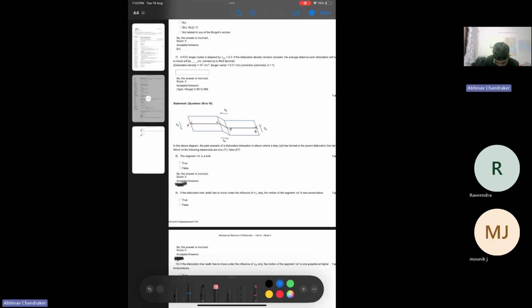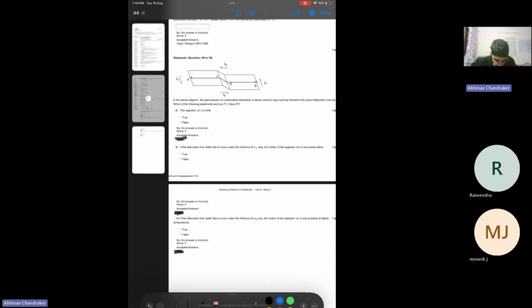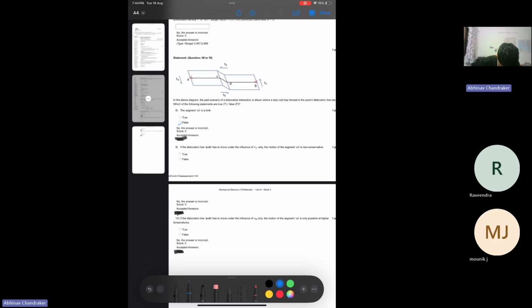Actually, if this is a screw dislocation, it cannot be, because CD has a different direction compared to BD. So the Burgers vector of BD will not be the same as that of CD if this is a screw dislocation, because a screw dislocation has its Burgers vector along the dislocation line. So a part of the dislocation is lying on a different plane compared to the other path. If AC or DB is the glide plane, CD is not on the glide plane. So CD should be called a jog. So the answer should be false.